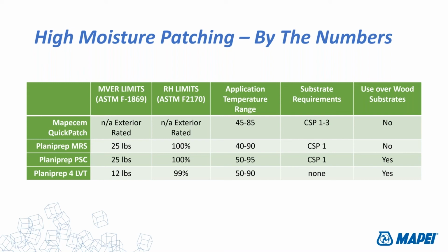Typically the application range is 45 to 85. You do need some porosity and texture of the concrete. They're recommending anything from a CSP of 1 to 3. And can you use this over wood substrates? The answer is no. Planiprep MRS, again, you'll see where we are on that one, 25 pounds, 100%.